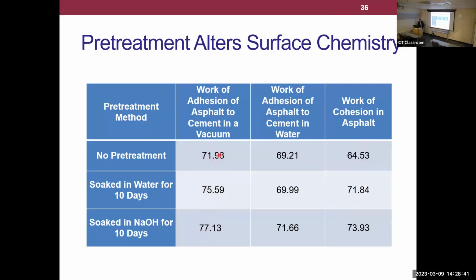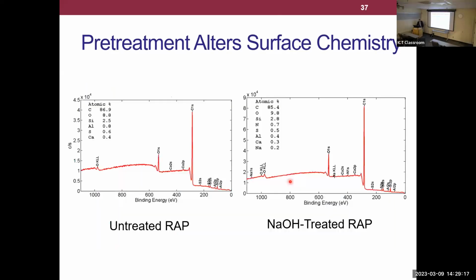So this is just plain asphalt. This is asphalt we soaked in water just as a secondary control. And this is asphalt soaked in that NaOH solution. So definitely we're somehow modifying that surface chemistry. And what you'll see here is when we compare this to the surface free energy of cement paste, we are seeing a slight increase in the work of adhesion. It's kind of like a chemical bonding mechanism, a slight increase. Is it really solving our problem? Probably not really. But we're still trying to figure out why is this NaOH affecting things?